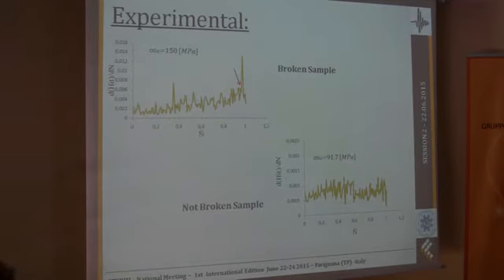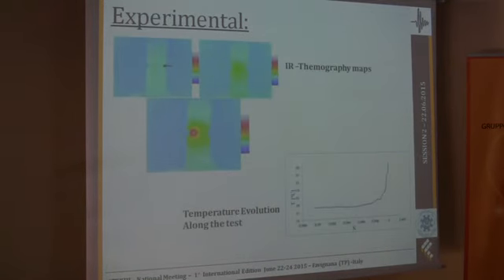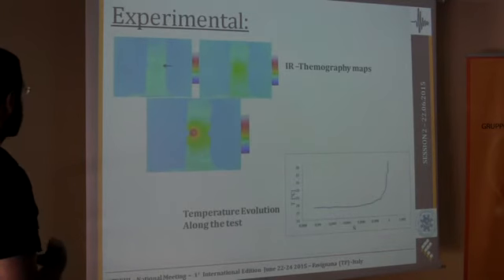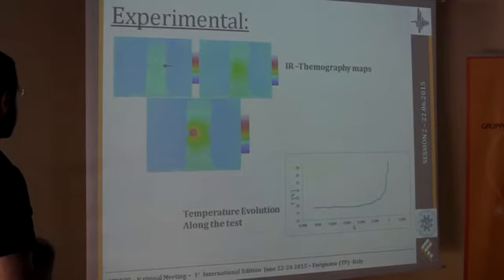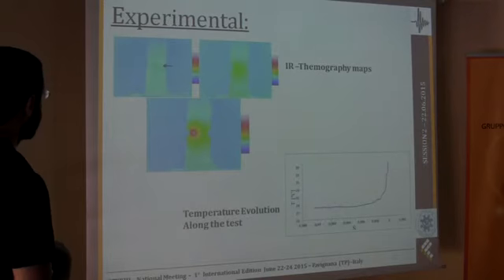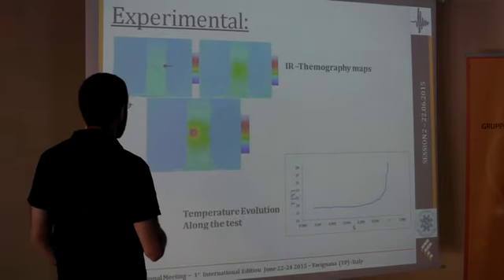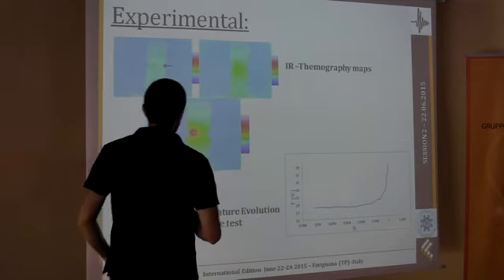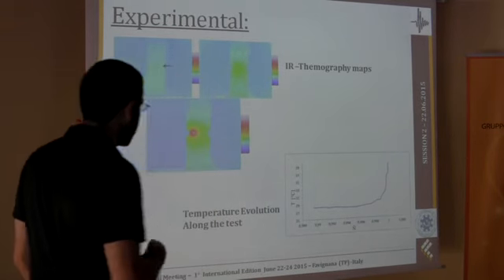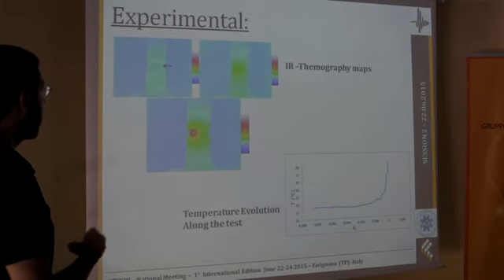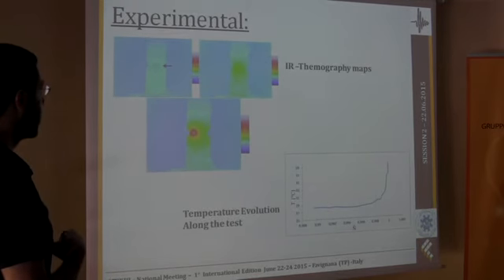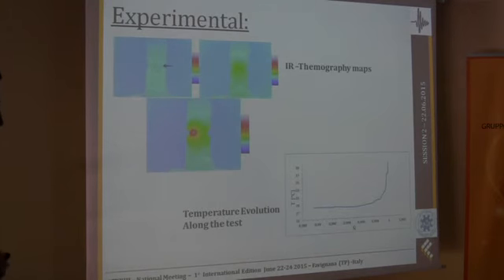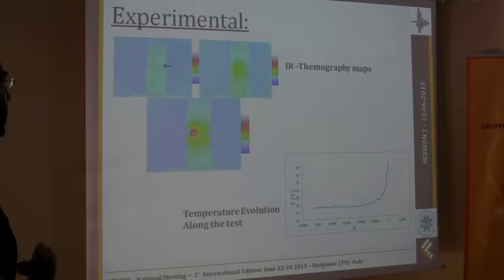And here are some just pictures now from thermography. Thermography confirmed that all the crack propagation occurs immediately from one notch to the other, just as observed in acoustic emission. But with thermography we were not able to observe the very initial stage connecting to the crack initiation. That's where they are very well observed with acoustic emission.